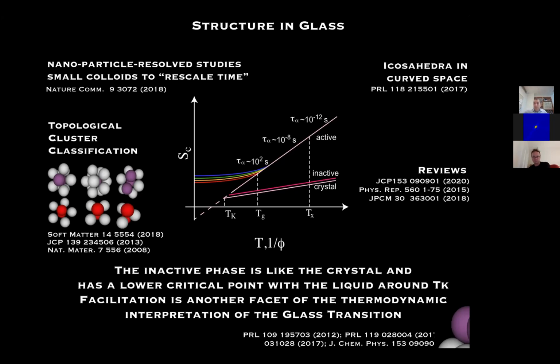But perhaps I can start breaking the ice. I do have a question concerning the approach you use to generate configurations which are very close to the Kauzmann temperature, introducing a bias on the local structure. In this approach, is there any relation to thermodynamic equilibrium? Can you really associate a temperature to these configurations, or do you just have more configurations, but you don't know if you are in equilibrium or not?